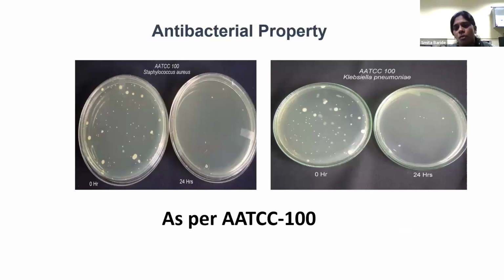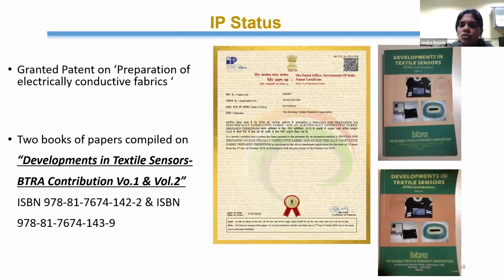And one more additional property this conducting polymer is found to have is an antibacterial property. That is its inherent property, because of the carbon nitrogen bond. So this way we have done a lot of work on conducting polymer coated samples. We have around 9 to 10 peer review publications on that, one granted patent for synthesizing this ICP based sample, and also a publication of 2 books, which include all our published papers.